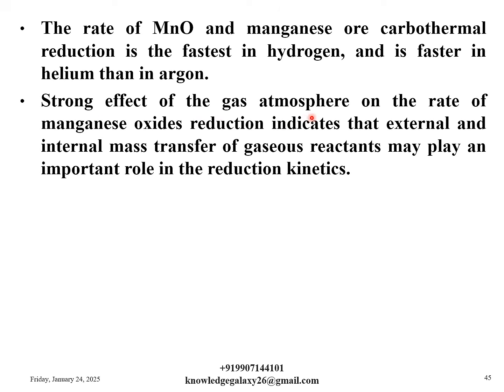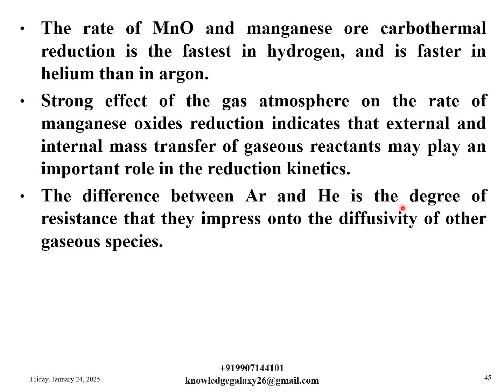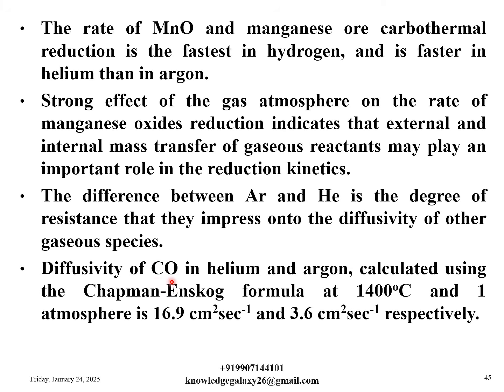Strong effect of the gas atmosphere on the rate of manganese oxide reduction indicates that external and internal mass transfer of gaseous reactants may play an important role in the reduction kinetics. The difference between argon and helium is the degree of resistance that they impress onto the diffusivity of other gaseous species. Diffusivity of carbon monoxide in helium and argon calculated using the Chapman-Enskog formula at 1400 degrees Celsius and 1 atmosphere is 16.9 cm square per second and 3.6 cm square per second respectively. The difference is a factor of 4.7.